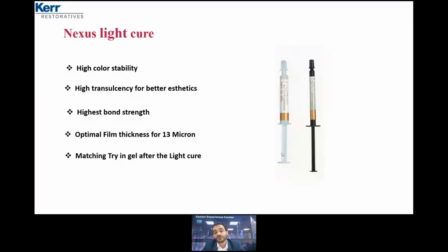You need to have a cement matching the try-in paste. I need my try-in paste to be similar to the veneer cement, yes, but after the light cure, not before. Because you know, for any light cure material like composite, like cement, you should add something called a light initiator, a chemical light initiator. Most of them use camphorquinone, okay? And the camphorquinone at the beginning seems yellowish in color. Once it interacts with the light, it will be more bleached, okay? So here, for any light cure composite or light cure cement, you have nil or very low change in the color. So you need the try-in to be exactly equal to the color of the veneer cement, not before the light cure, but after the light cure, in order to decide the shade that you need.